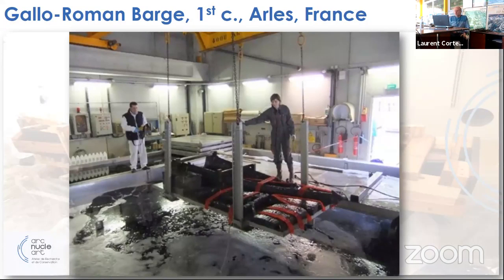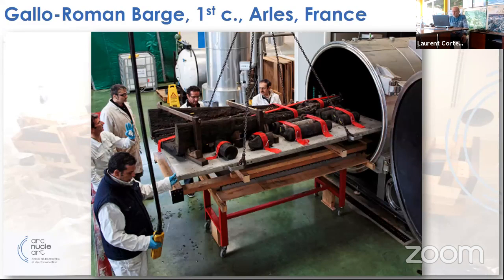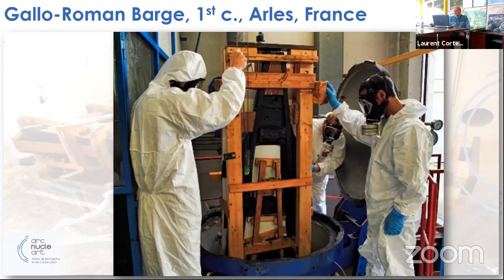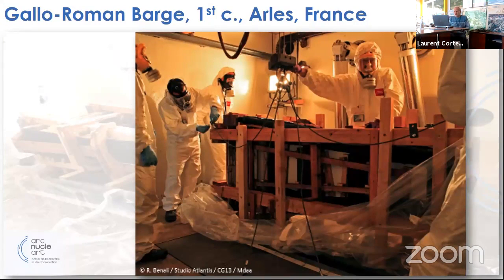So you can see the PEG impregnation step with our big pool of impregnation. Then the freeze drying. Here you can see also pieces of the mast that was also treated with the same nuclear techniques, because it was well adapted to make it solid enough to be presented in a vertical position. Then the vacuum pressure impregnation of styrene polyester. And finally, the irradiation. You can see here the handling inside the irradiation chamber with cleaning of the excess of resin.